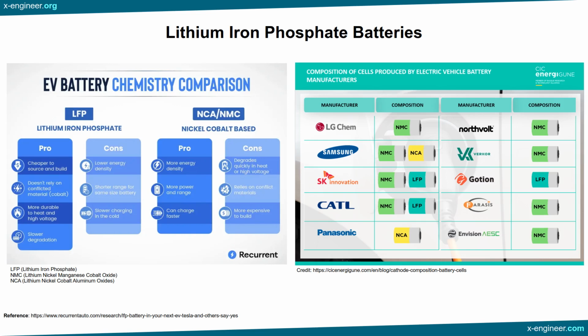Lower fire risk. Lithium-ion battery fires are usually due to extreme heat conditions, and are triggered by something called thermal runaway, which happens when the temperature of the pack exceeds a certain limit. For LFP batteries, thermal runaway temperature is at 270 degrees Celsius, as compared to 210 degrees for NMC and 150 degrees for NCA. This makes them super safe for on-the-road uses.